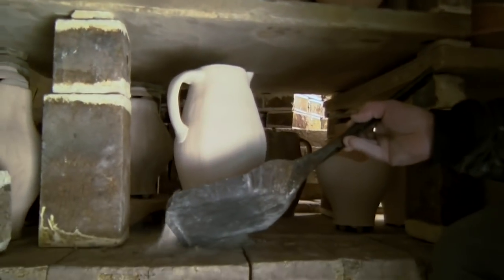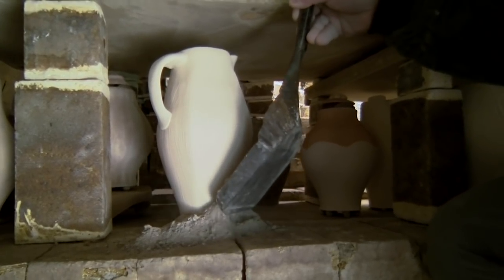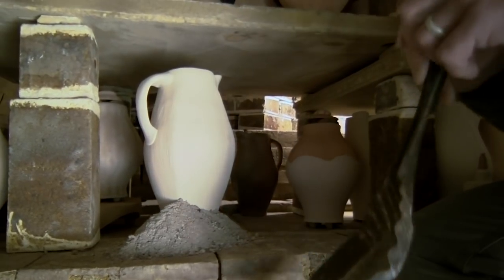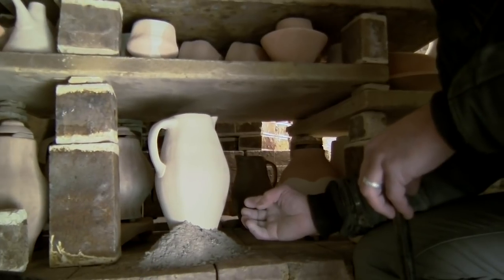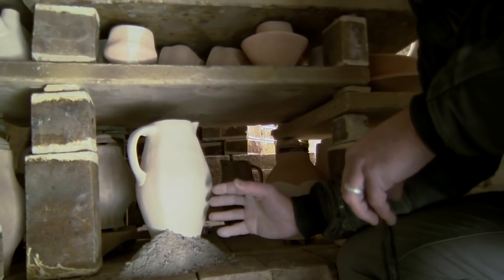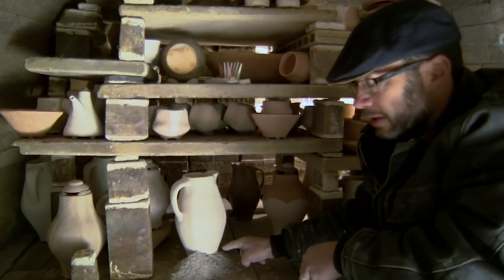The reason I call it mulching is because I'm putting it up around the base of the pot, and I'm creating a horizon line right along here. What will happen during the firing is the ash will shrink a little bit and pull away, but it'll insulate and adhere to the pot. It can leave a very sugary quality of ash, and I've seen purples and greens and some beautiful stuff right along that horizon line.